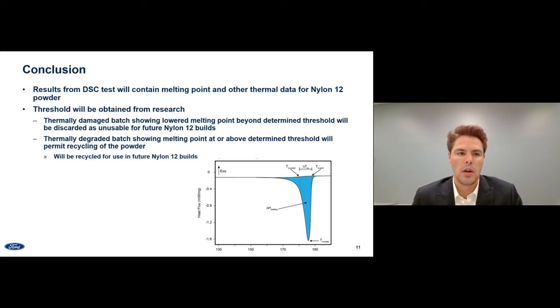A threshold for discarding thermally degraded material will be obtained from research, and thermally damaged material that is below this threshold will be discarded and not used for future nylon 12 builds. The thermally damaged batch that is above this threshold will be mixed with virgin powder and used in future nylon 12 builds. And overall, when Ford implements DSC testing, they'll be able to determine which materials are thermally degraded and if the powder can be mixed 50-50 with virgin powder, and will get reliable material quality data so they can produce quality parts for their nylon 12 builds.